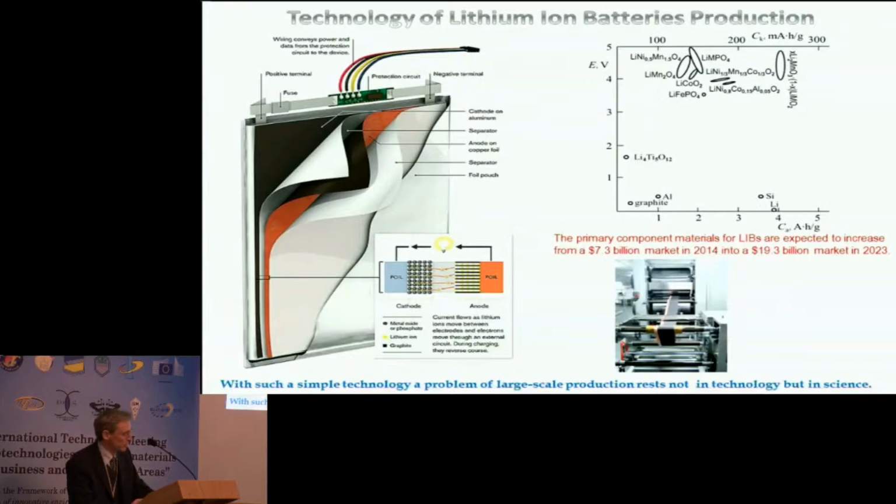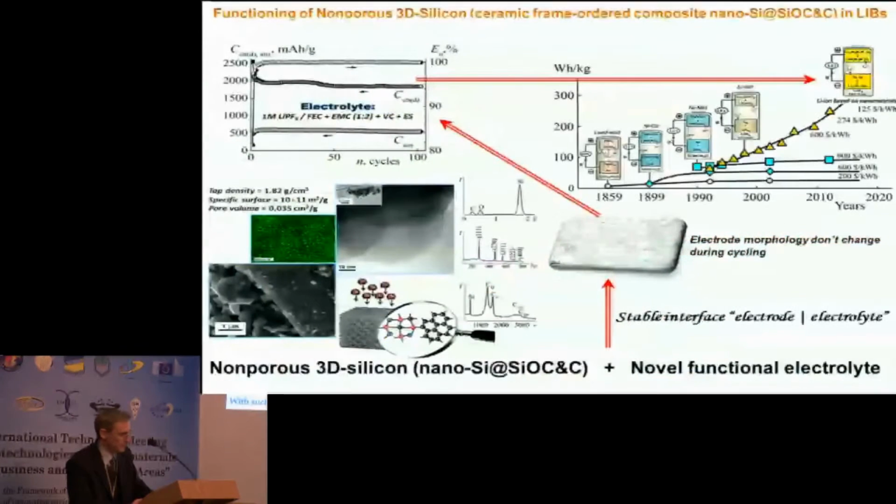As promising materials for the positive electrodes, considered stable in air, are lithiated layered oxides, fluorophosphates, silicates, and structurally integrated composites. Interesting candidates as new active materials on the anode are typically metals or semi-metals, which are able to electrochemically and reversibly form alloys with lithium. These materials exhibit very high theoretical rechargeable capacities due to the higher amount of lithium which can be reversibly stored in alloys compared to carbonaceous or graphite-like carbons, which exhibit an intercalation-based storage mechanism.